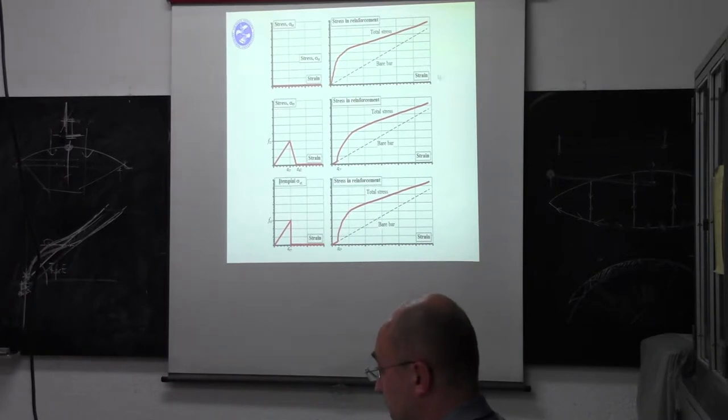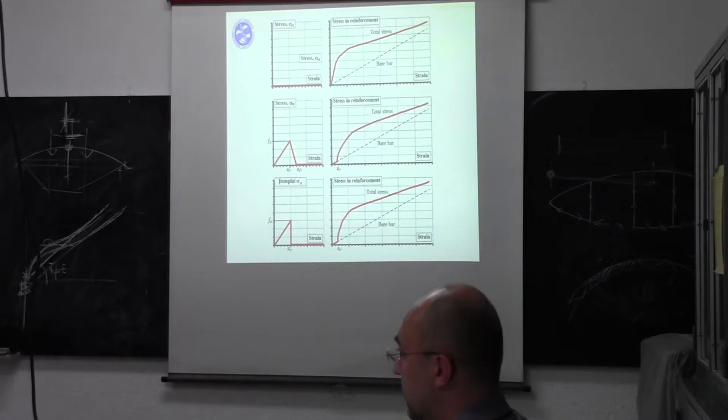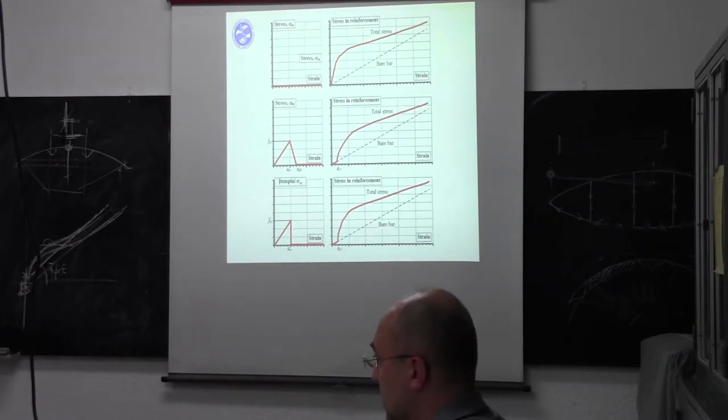assigned to bar reinforcement. What is the advantage? This model you can use in any finite element code that allows specifying material models. This model does not require any descending branch that very much complicates calculations. For instance, this model was applied in ANSYS, which completely does not allow performing any calculation with concrete, and we obtained the same results as was modeled.